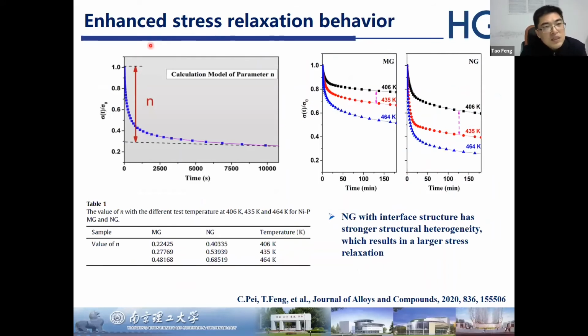And for a long period, people always thought the metallic glass has a uniform structure. However, just recently, people started to realize structural heterogeneity is an intrinsic feature in metallic glass. And stress relaxation is one of the effective methods to measure this structural heterogeneity in metallic glass. Here, in principle, we know the nanoglass with the interface structure has stronger structural heterogeneity, so it results in a larger stress relaxation as shown in the table.